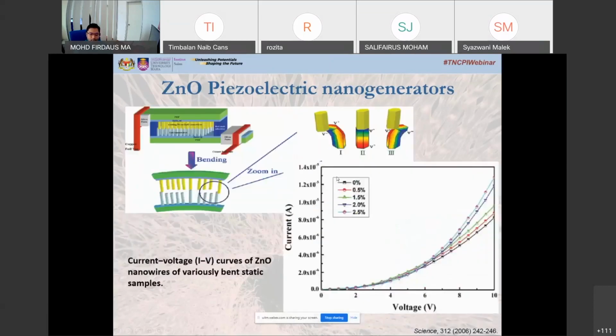Okay, so this is the result of the bending. It was increased from 0 until 2.5%. So we can see the current increases with the bending percentage, indicating that the impedance decreases as the compression increases. So this suggests that the area of contact between the nanowire and PT nanowire increases with the compression until the sample is deformed.